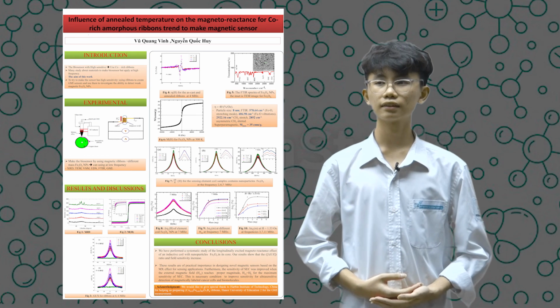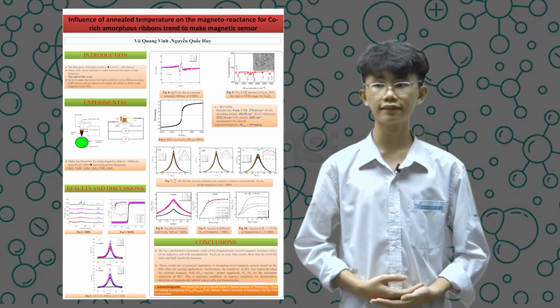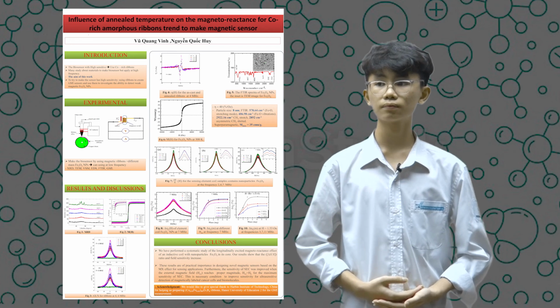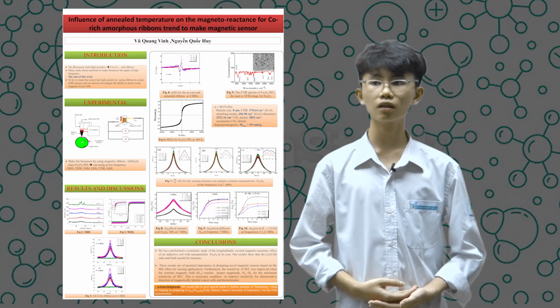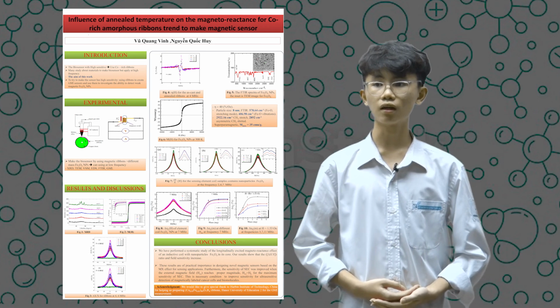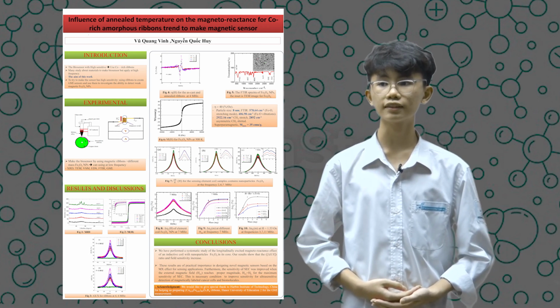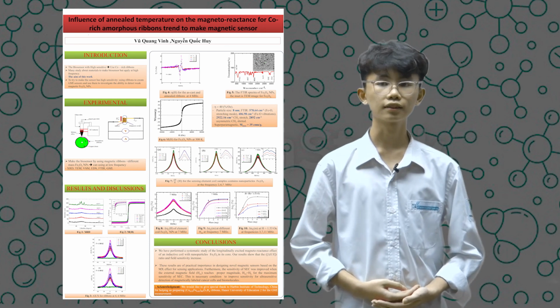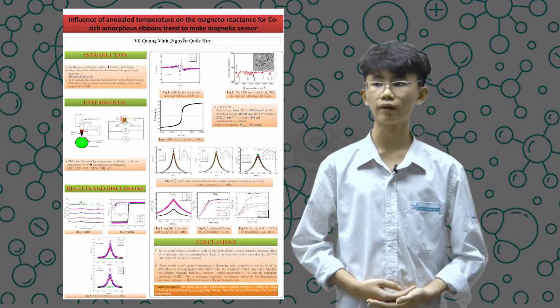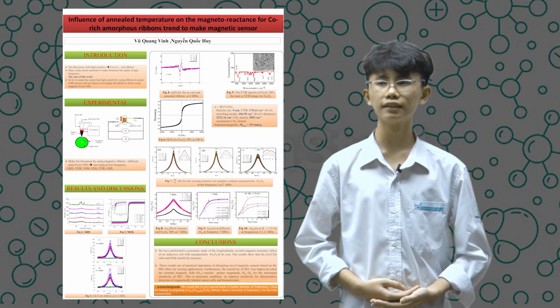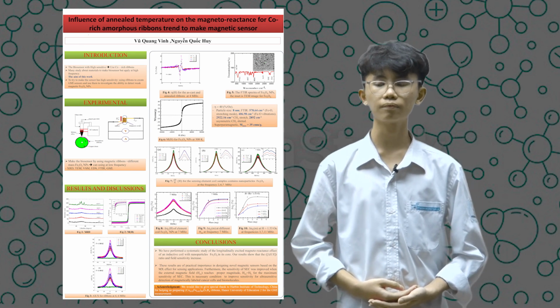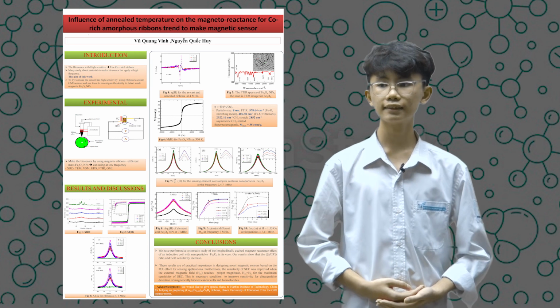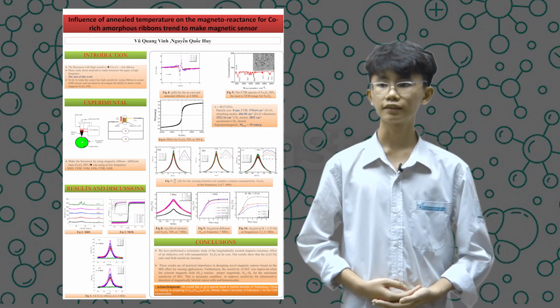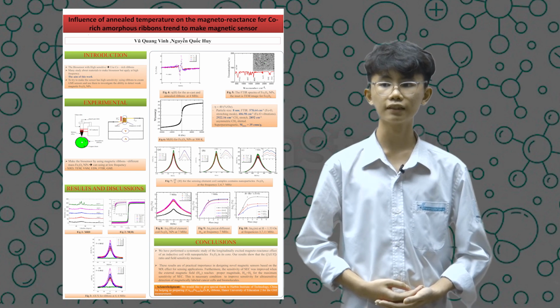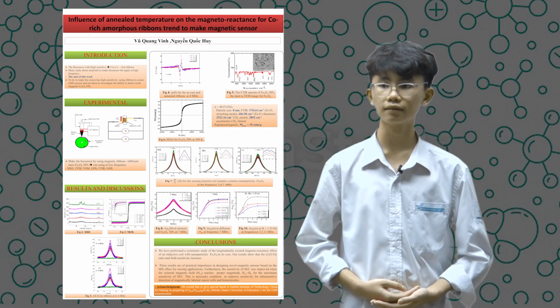Our result shows that the delta X per X ratio and field sensitivity increase. This result has practical importance in designing novel magnetic sensors based on the MX effect for sensing applications. Furthermore, the sensitivity of the sensor was improved when the external magnetic field He reaches a proper magnitude. He equal to Hk gives the maximum sensitivity of the sensor. This is a necessary condition to improve sensitivity for ultra-sensitive detection of magnetically labeled cancer cells and biomolecules.